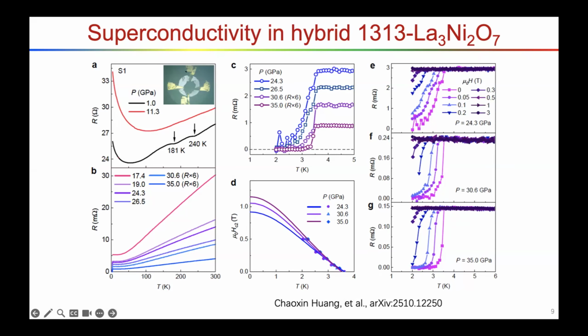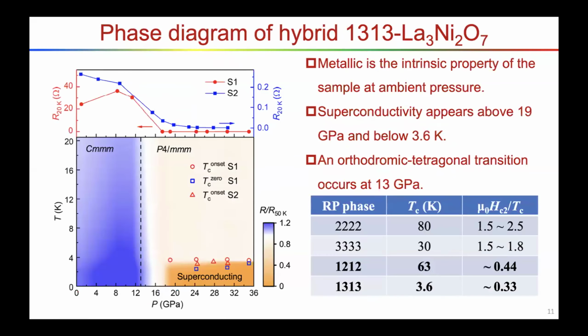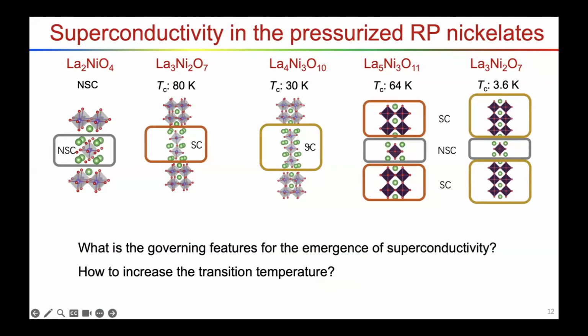Well, for the trilayer phase, people have a consistent conclusion. In the trilayer, there are intertwined spin density wave and charge density wave. It was first proposed by John Mitchell's group, and I think it's widely accepted. Recently, our collaborator Xingjiang Zhou's group posted a paper on arXiv, I think yesterday. They propose it's a Fermi nesting driven spin density wave. The data are perfect. And for the bilayer phase, the spin density wave or magnetic order is very weak. I think it's also a spin density wave, or Fermi nesting driven. I think itinerant electrons play a more important role.